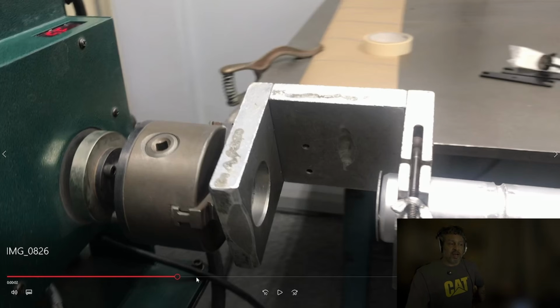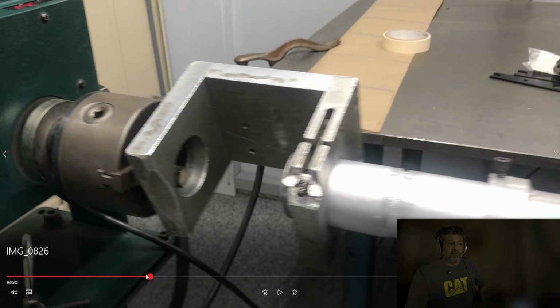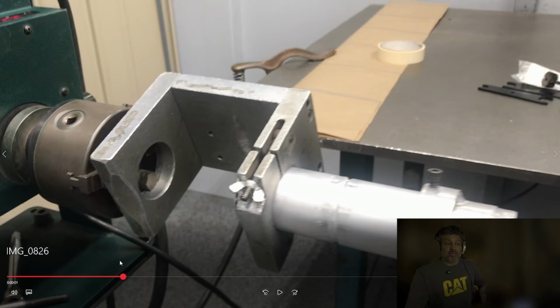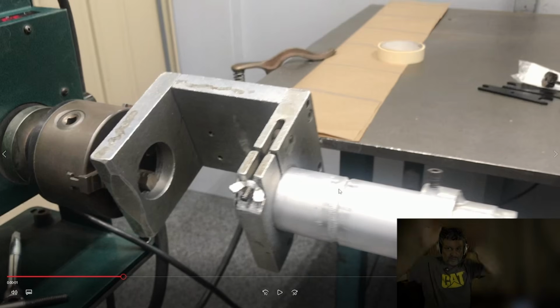Now, the key to actually passing this weld test is being patient, waiting. When I took this same weld test in Inconel, once you hit the pedal to rotate the positioner, you could basically just keep it going at a slow speed and the penetration will be even. With this piece, no, you don't want to do that at all. You want to start the puddle and you'll see the aluminum sink in, you'll see it puddle up and then dramatically move down. That means you got penetration.